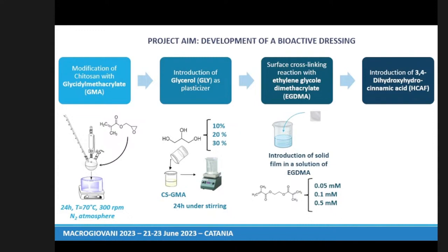In particular, we decided to develop a surface cross-linking. In fact, our matrix was immersed in a solution of EGDMA at 3 different concentrations. In the end, to introduce antioxidant properties and to increase the antimicrobial properties of chitosan, we decided to introduce 3,4-dihydroxyhydrocinnamic acid, named HCAF, using 2 strategies.